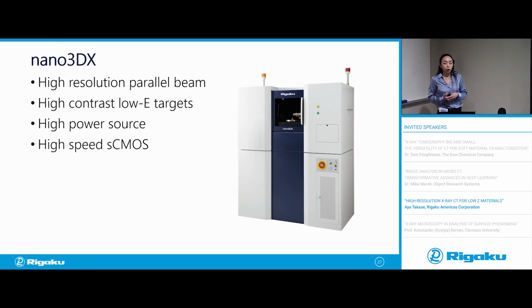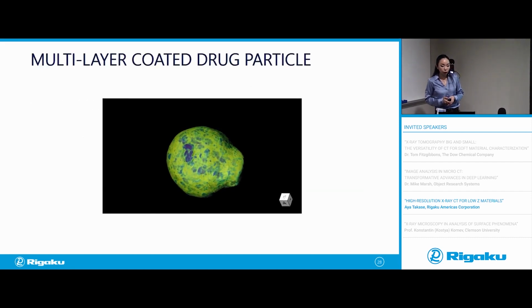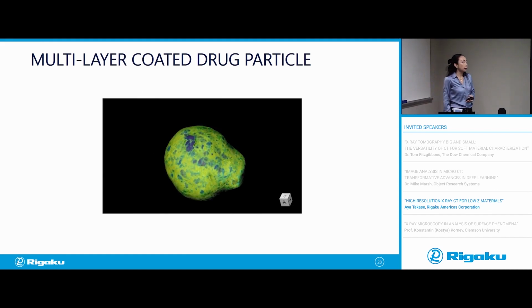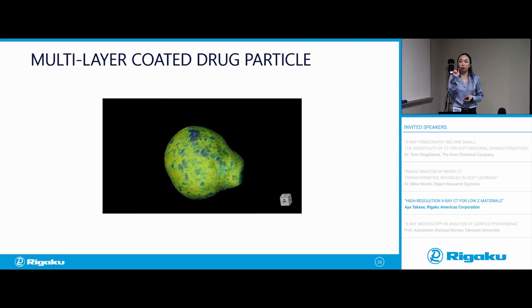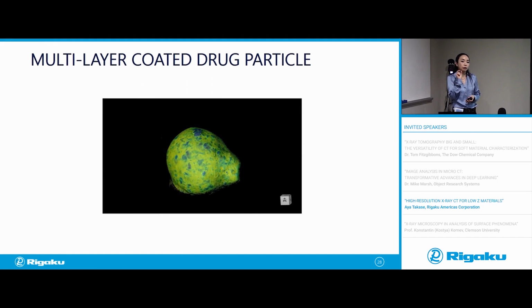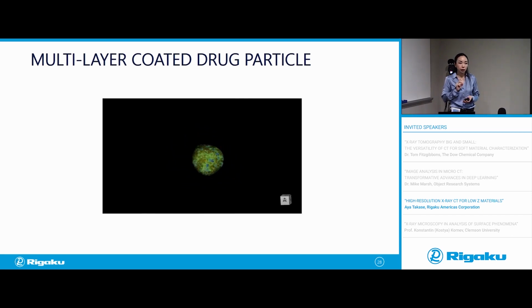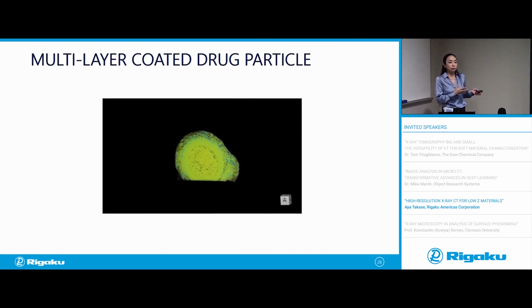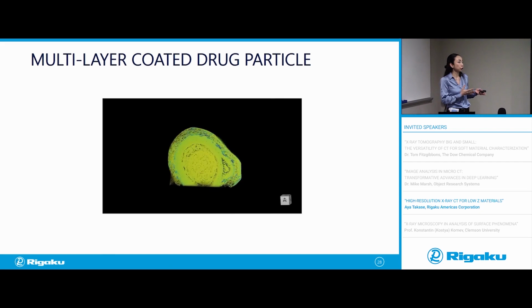So I would like to show you some examples of CT scans we collected on the Nano 3DX. This is an image of a single, about 0.5 millimeter diameter particle of, I think, a heartburn medication. I just took one particle out of a capsule and scanned it with copper radiation on the Nano 3DX. So considering the size of the sample, you can see that this is a very high resolution scan. It's a submicron scan.